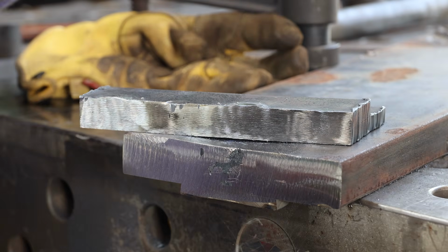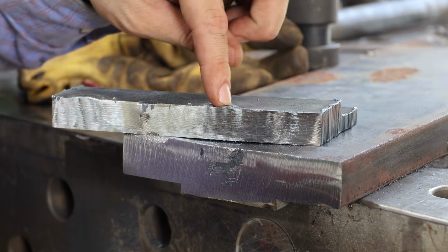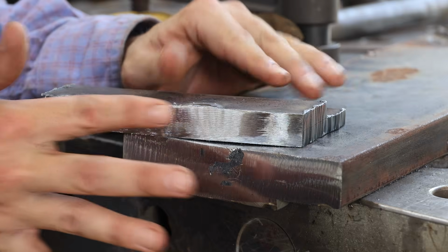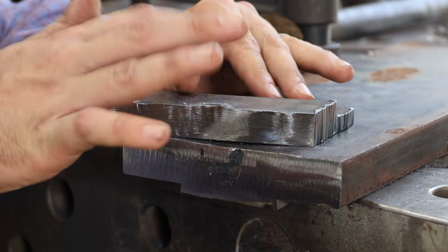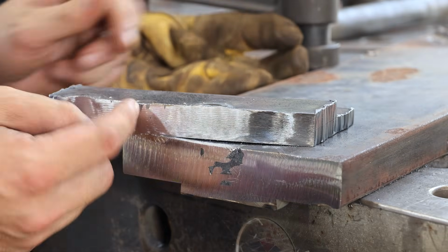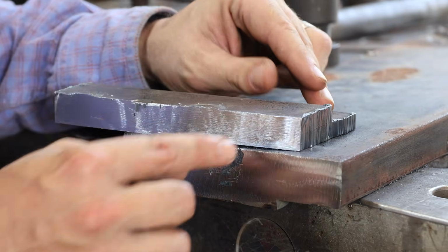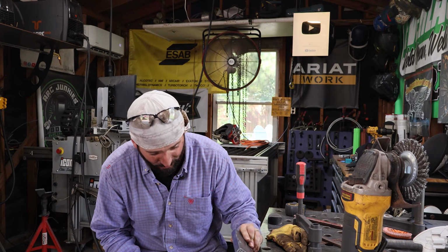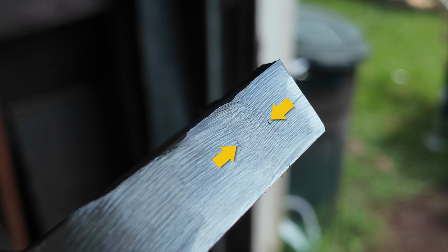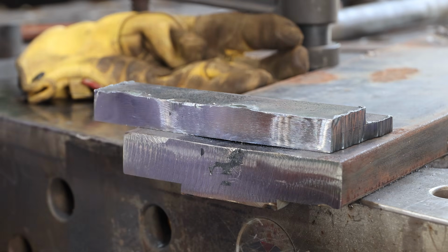Moving out of the slaggy process, flux core, going to MIG, hardwire, we have a nice smooth sound weld right here on the big hole. On the little hole, we don't see any of the trapped slag in the corners. And at first glance, you're like, oh, that was probably just works better. But if you shine a light around a little bit, we have two clear as day lines of lack of fusion, where again, we did not get down to the root and get the root finished before filling up. Just not enough space, so we didn't get the fusion.